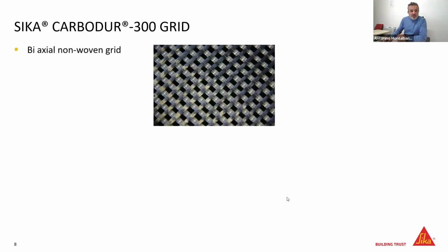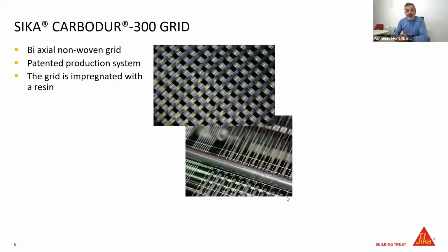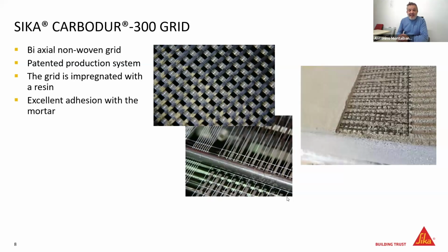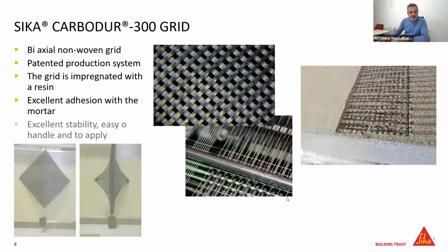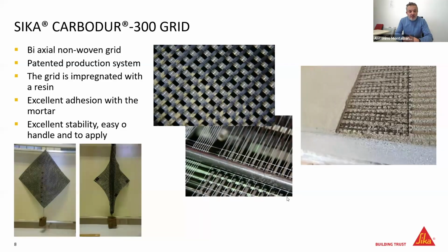The grid is quite special, it's a biaxial non-woven grid. Non-woven means that both the warp and the weft are plain without any weaving. The production system is patented and it's not a dry fiber, but the grid is impregnated with an acrylic-based resin, and this dramatically improves the adhesion with the mortar. And thanks to this impregnation, the grid is stable, easy to handle, and easy to apply.